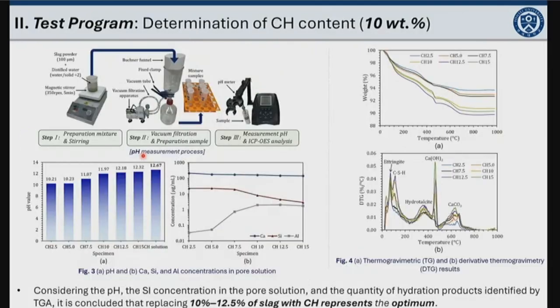The pH in the pore solution, as you can see here, increased by increasing the amount of calcium hydroxide. Most importantly, from 7.5 to 10%, there was the largest increase of the pH value. In addition, the silicon concentrations in the pore solution start to decrease obviously from 7.5% of calcium hydroxide, meaning a lower calcium to silicon ratio in the CSH gels, which is effective for strength enhancement.